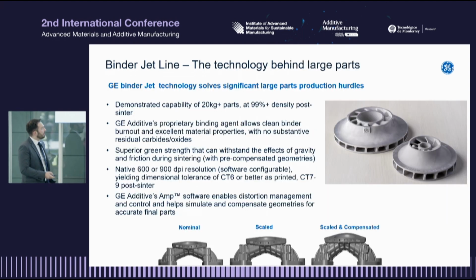Okay. On the right-hand side of the screen, I want to show you two things that I'm allowed to show you, because there's a component that belongs to a customer that's, I think, 22 kilograms in mass. If you're American, you want to talk pounds, but 22 kilograms in mass that is perfectly well sintered, and its thickest cross-section at 3 centimeters is dense from edge to edge. This is because of the sinter cycle that's applied, as well as that AMP compensation software, and the very consistent powder bed density that we have when the part is printed.